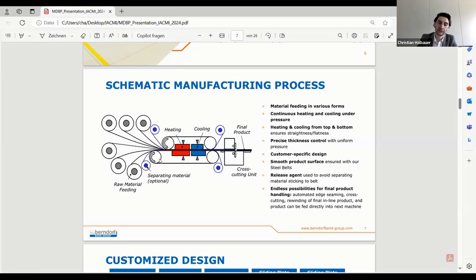Once we enter the press, we start at the drums on the bottom and on the top. Usually those are preheated at a temperature of around 120 degrees. They're preheated with thermo oil. Within the press, I'm gonna go into more detail a little later on. Just a rough indication, we divide into a heating and a cooling section.